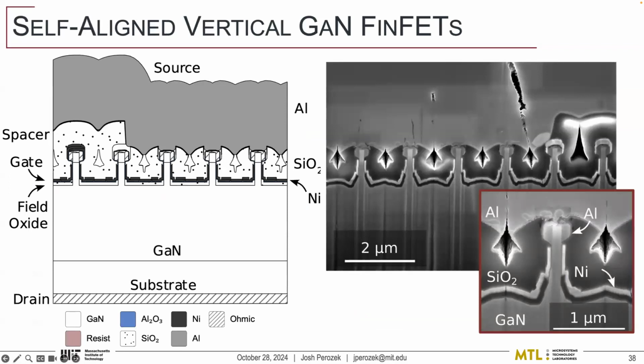As you can see from this cross-sectional SEM here, we're able to get a very close match. This was the first attempt at making this. We achieved sub 500 nanometer gate length on these FinFETs. Entirely self-aligned, follows exactly the process that we had described. Without any restrictions on lithography, all in the first shot, which was great.